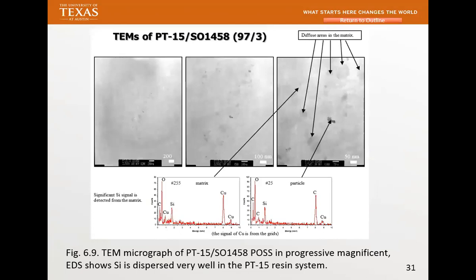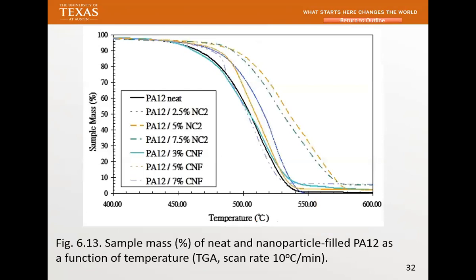Clay and POSS are very different. POSS is a different nanomaterial than any other, because when you work with the other nanomaterials, they don't disappear. For clay, it will make for better dispersion, but you still see the same clay. But POSS, if you use it carefully, you will be able to have this kind of molecular dispersion. And the property changes quite a bit. So that's what we did in one of our research projects. It was sponsored by the Air Force. So another thing that we do a lot is what we call TGA.